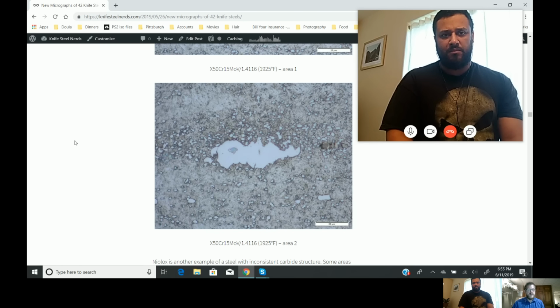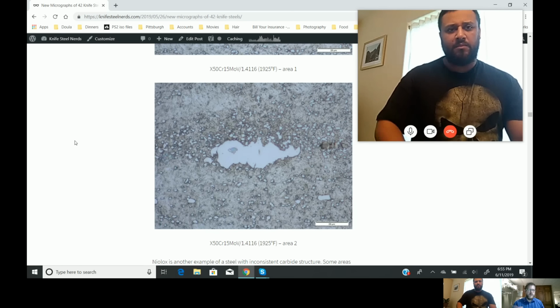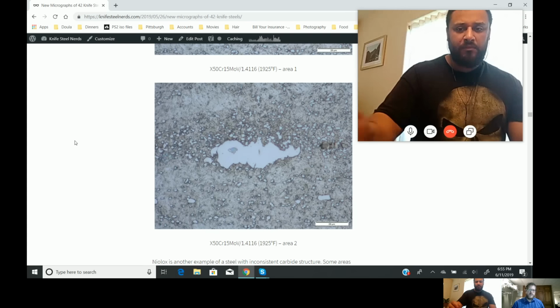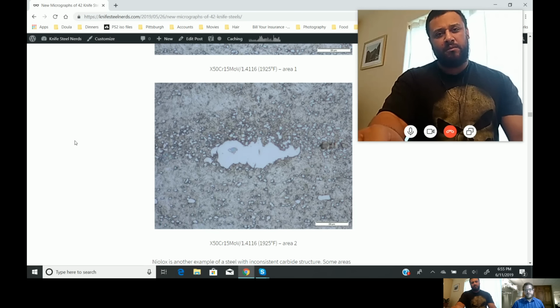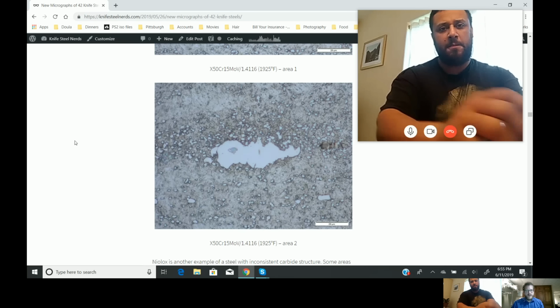But during slow solidification, the chromium wants to bunch up with itself. And so you'll have local areas of high chromium, and those can be very difficult to eliminate when you form a carbide like that.